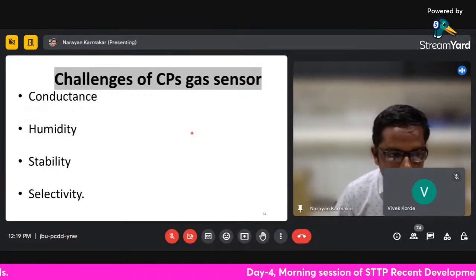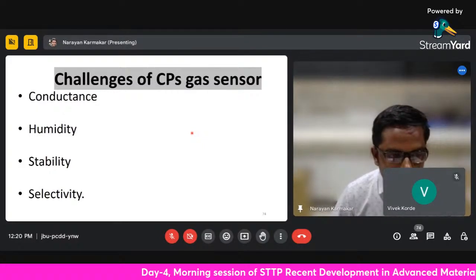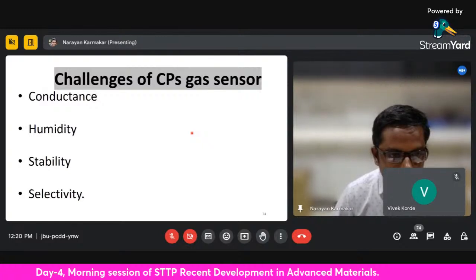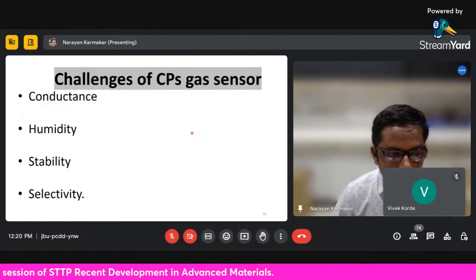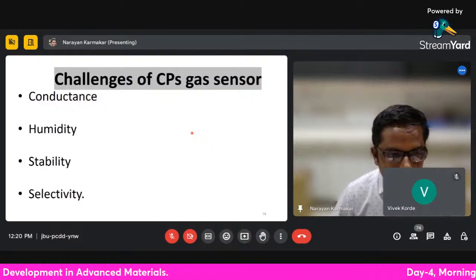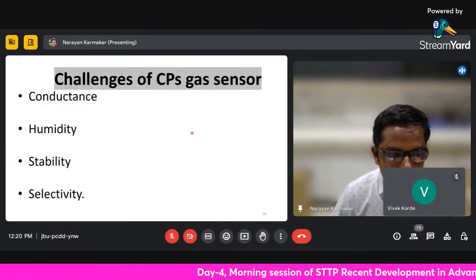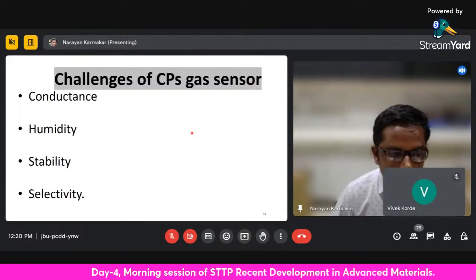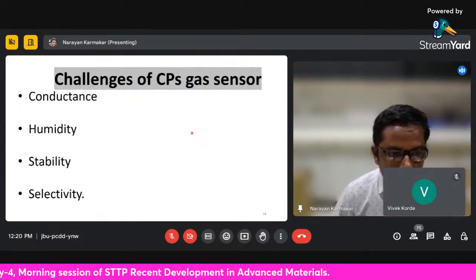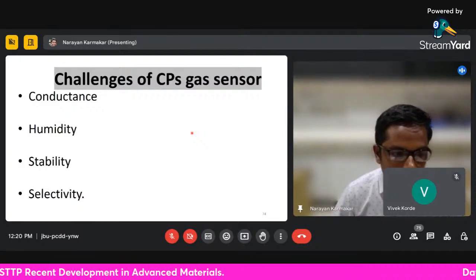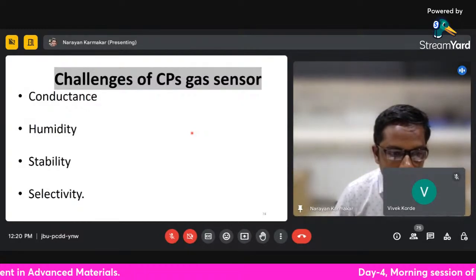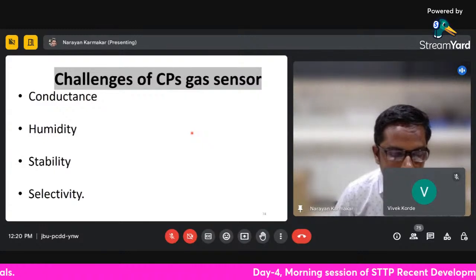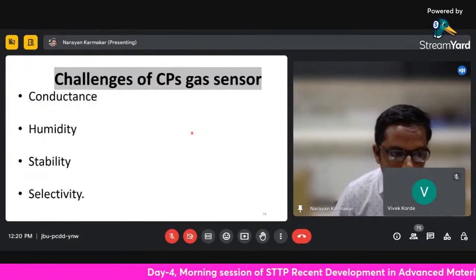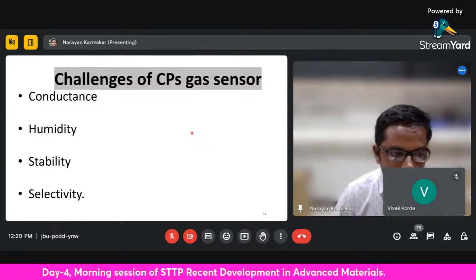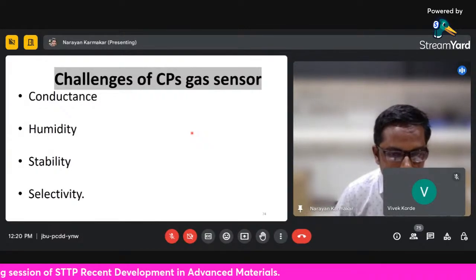And also the last part that we saw is the selectivity of this gas sensor. In all the previous slides, we saw the different gases. It is not sensitive only to the target gas, but also to the other gases. So when you design a gas sensor, make sure that you functionalize the material, the conducting polymer, or change the parameters of the nanoparticles, so that it is selective to a specific gas. If it is not, then selectivity is a major challenge.